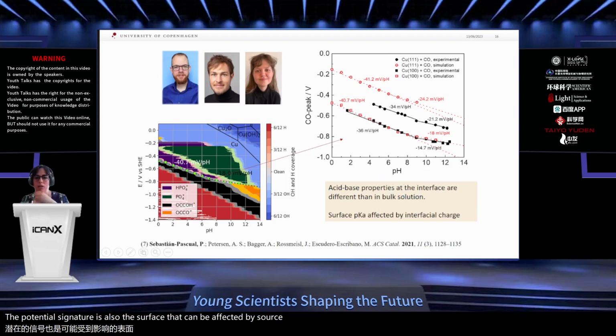So basically, the conclusion of this is that the copper electrolyte, the metal electrolyte interface structure, is controlling the potential window that we need to adsorb CO on the surface at different pH, and this can affect the onset potential for the CO reduction on copper.